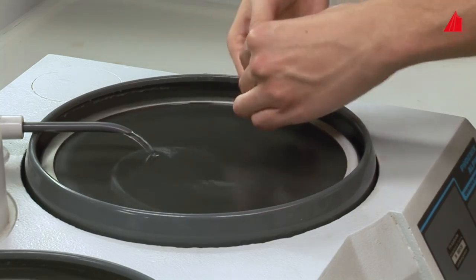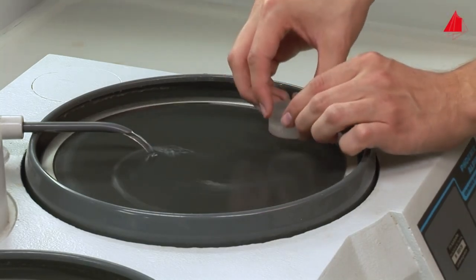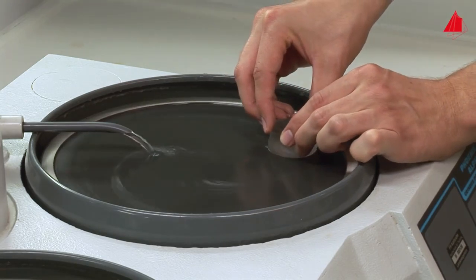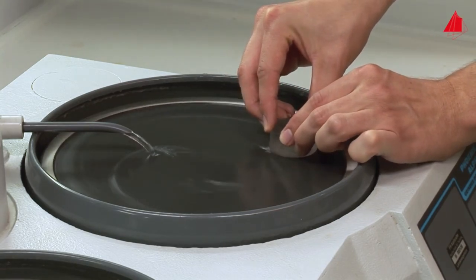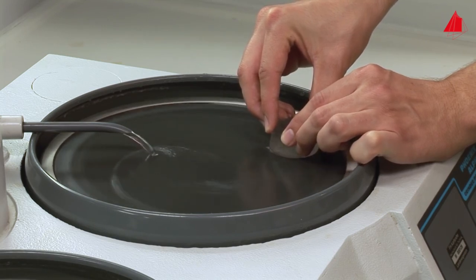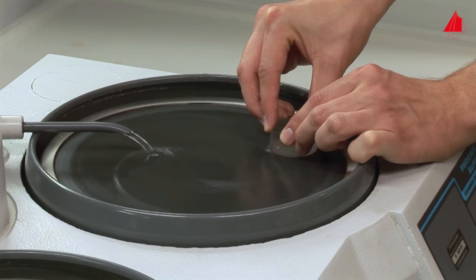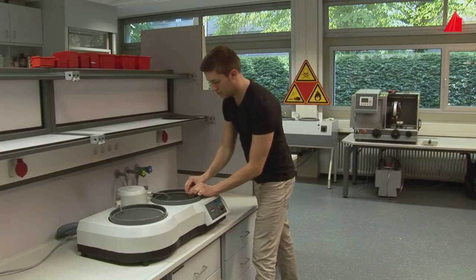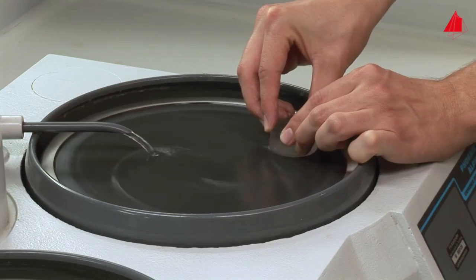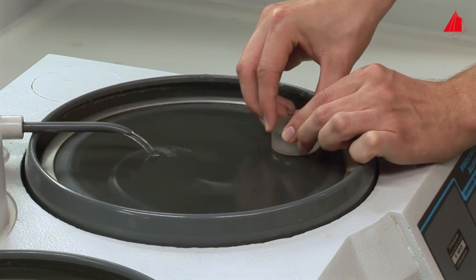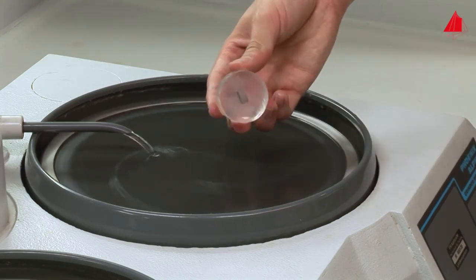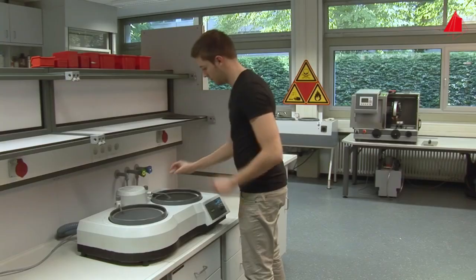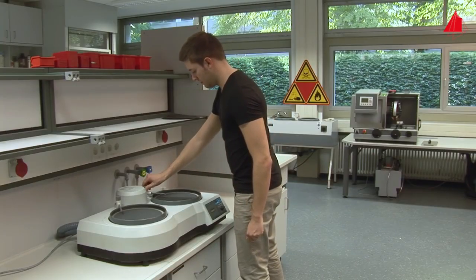Now comes the most important part, the preparation of the intended plane of examination. Our material tester begins with comparatively coarse 180 grit abrasive paper. He makes sure to press the specimen calmly and evenly onto the abrasive paper, compensating the tendency for the sample to tilt. He also makes sure not to grind his fingertips accidentally. Now he has achieved an even, relatively rough surface. The specimen is ready for the next step with finer paper.